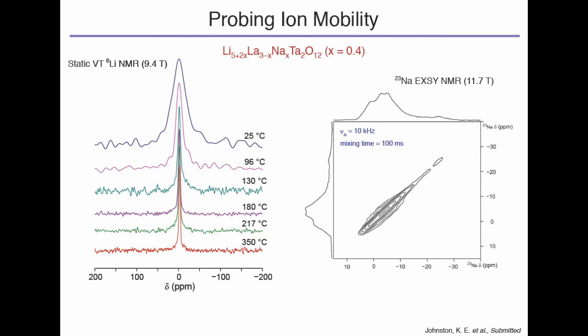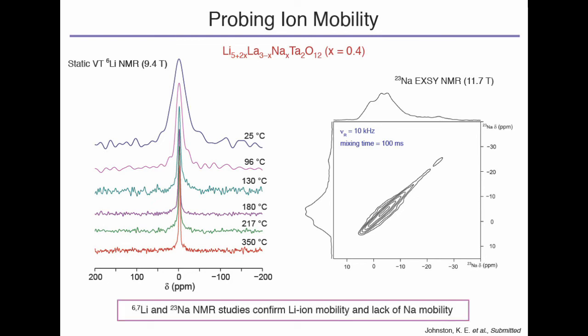If you do get exchange of those two sites, you will see what's referred to as cross peaks, which is any type of peak off the diagonal. It can be up here or it can be down here. We did this for a range of different conditions, and it turns out we don't have any exchange of any sodium sites. So wherever the sodium is going into the structure, it's going in and it's staying there, it's not moving. So it's not contributing to the ion conductivity of this material. These studies confirm lithium ion mobility, but a lack of sodium mobility.